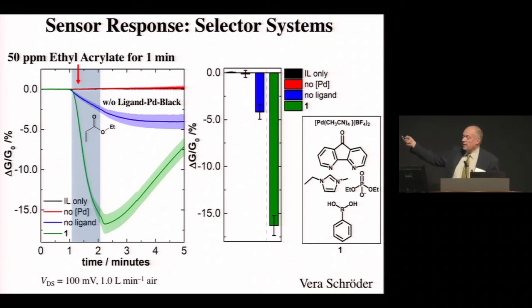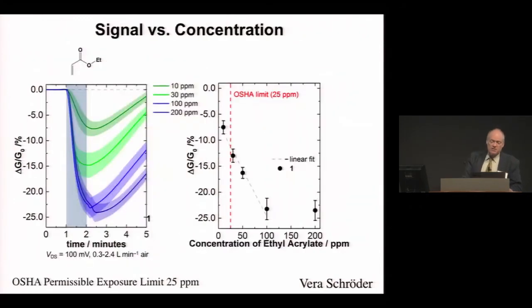But if we put in the catalytic mixture that Shannon put together, and we add our alkene, ethyl acrylate, a toxic monomer that people use on giga scale to make polymers, we get a really strong reduction in conductivity, because this is taking the palladium-2, going around that catalytic cycle and making some palladium-0, which is killing the conductivity, and then this starts reacting with it and bringing it back. Okay, it has reasonable linearity that you would like for analytical chemistry, and makes the OSHA permissible limits.